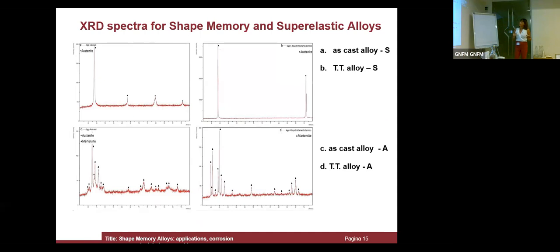The first two spectra are XRD spectra, so they give information about the crystallographic structure of the samples. Here we have the as-cast, so before any treatment, and the second one is after heat treatment. So it's possible to see that the peaks of austenite are well oriented. These two spectra are related to a cast alloy with a shape memory form. And here we have an improvement of the XRD thanks to the thermal treatment, because it's really, really important to operate with the samples